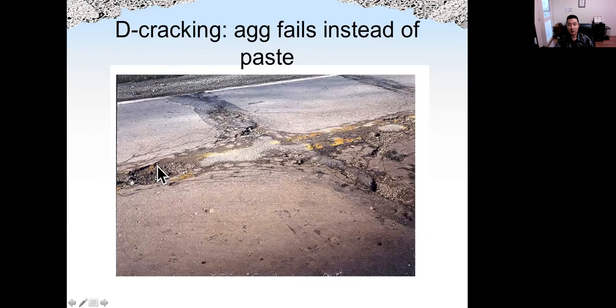So this is the so-called D-cracking. D-cracking is caused by porous aggregate. So when the aggregate is porous and we have moisture in this porous aggregate, and when the temperature drops down, the aggregate may fail instead of the cement paste. And that will form this kind of cracking pattern. We call that D-cracking.